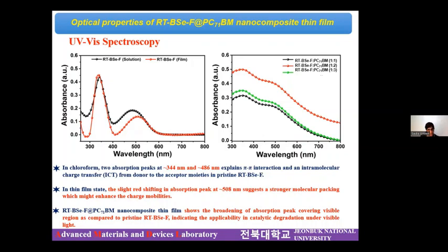enhance the charge mobilities. Whereas if you look at the UV absorption spectroscopy of the composite material, it shows absorption in almost the entire visible region, which itself is very promising because this kind of materials show their applicability in catalytic degradations under visible light.